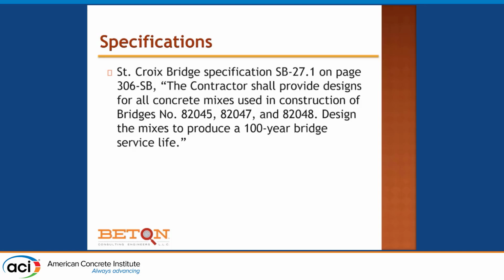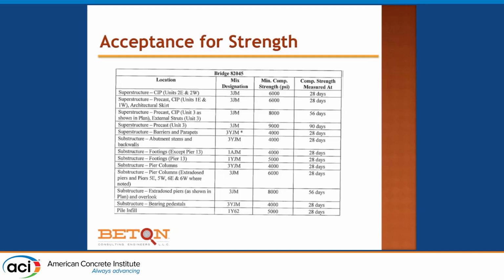So we do some mathematical modeling, we do a bunch of things, and then of course the structural engineer also says, hey, we need a bunch of requirements for strength, and so we have superstructure is a 6,000 psi at 28 days. The precast, cast-in-place elements and external struts, they need to be 8,000 psi. You can wait for 56 days for those. And then the superstructure precast elements need to be 9,000 psi, but you can wait 90 days for them.